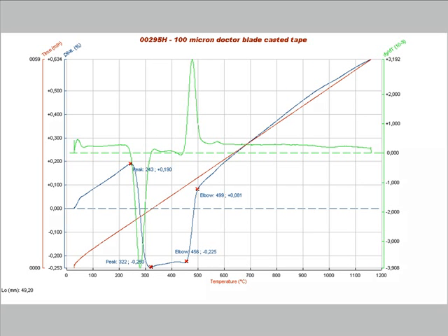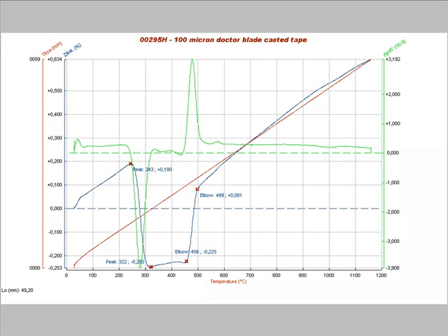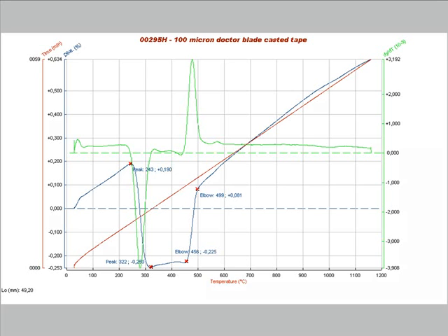This is the graph of the test on the green ceramic tape with a thickness of 100 microns. The material starts expanding, but it undergoes a sharp contraction, which starts at 243 degrees Celsius, and it ends at 322 degrees. This volume reduction is caused by the burnout of the binder. Then, it stays quite stable up to 456 degrees, but at this temperature, it expands rapidly up to 499. After this, it keeps expanding smoothly again. This is an unexpected behavior for this kind of material, and it was investigated deeper.